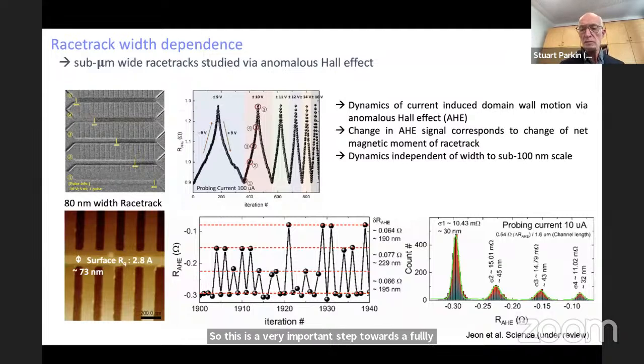So this is very exciting. We've now gone from micron-sized racetracks to 73 nanometer wide racetracks in which we can move domain walls equally efficiently, but we can now position them using this anomalous Hall signal to positions with an accuracy of a few tens of nanometers. This is very close to what we would need to build a super dense racetrack memory.